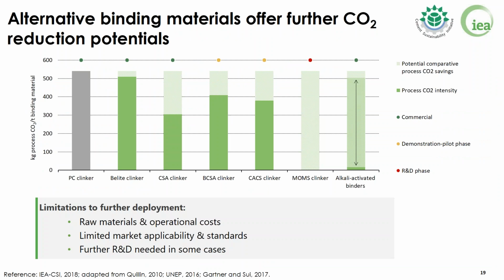One other element related with composition of cement that you will find in the roadmap is a very specific spotlight on alternative binding materials. They indeed offer opportunities for process CO2 emission reduction by using mixes of raw materials and alternatives compared to Portland cement. However, their commercial availability and applicability differs widely, and there is currently no independent publicly available or robust life cycle assessment for comparative quantification of production costs. For this reason, we consider it premature to include them in our technology roadmap in terms of real contribution to the CO2 reduction in the long term.